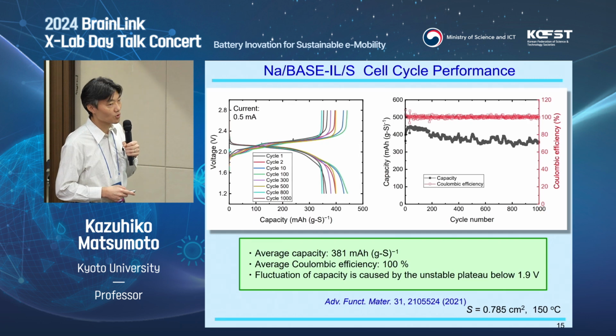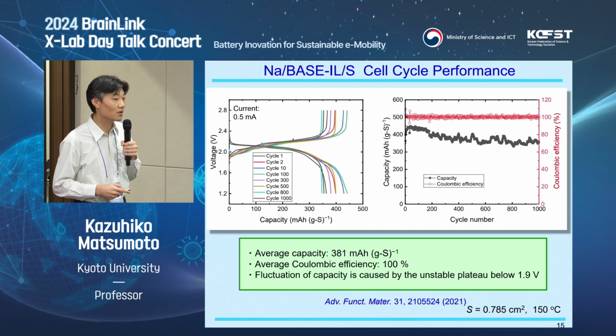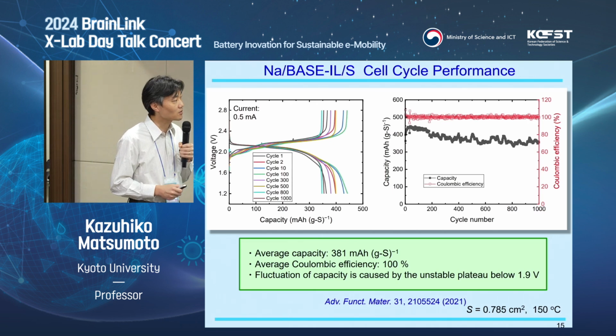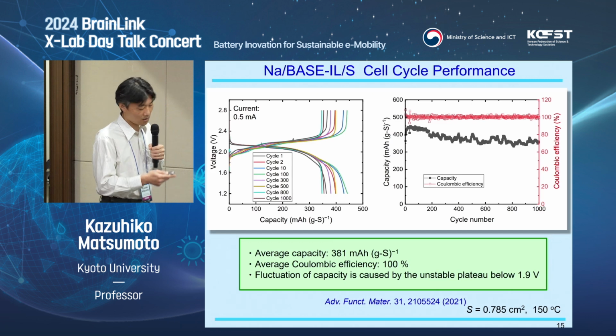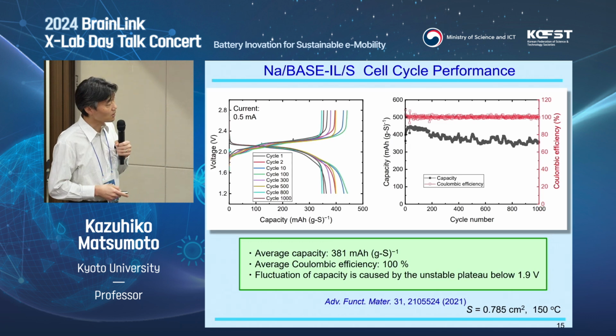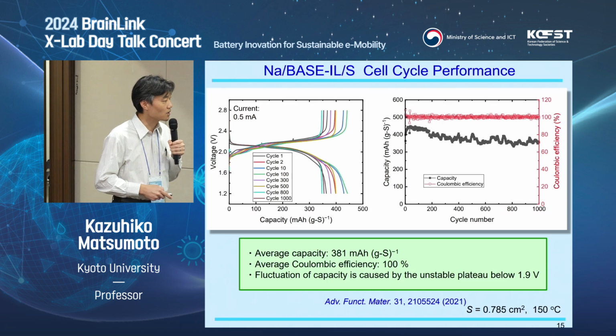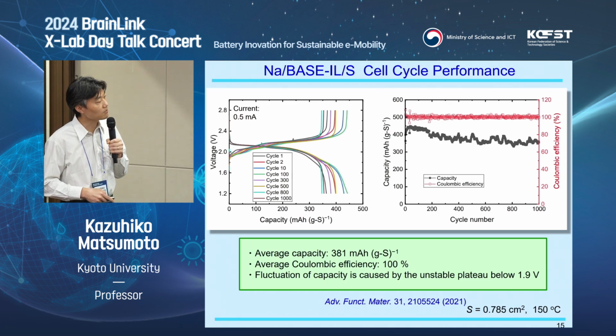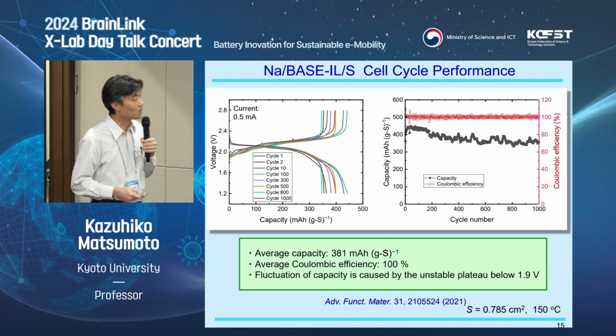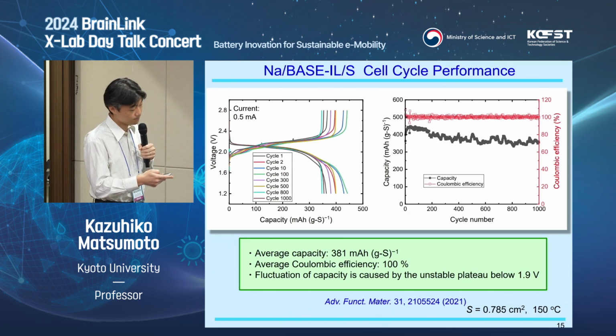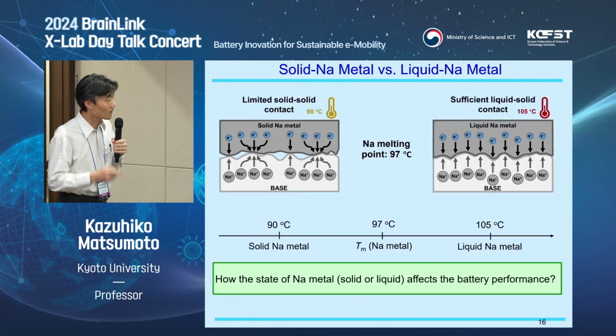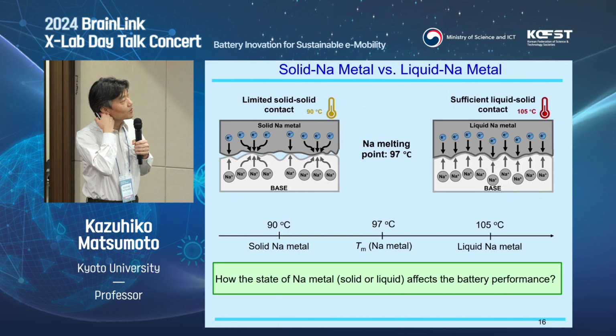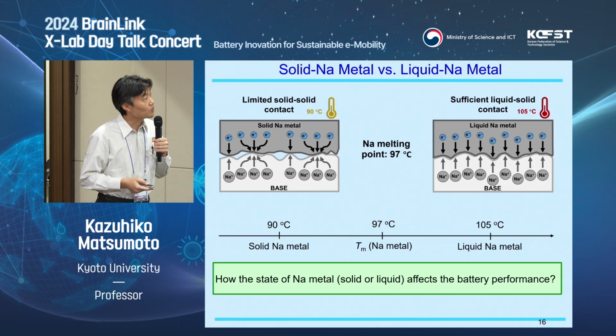We are still not sure why, but in this low voltage region, sometimes we can use that capacity and sometimes we cannot. There seems to be some surface contact that can affect such activity, but still we see the average capacity of 381 milliampere hour per gram, and Coulombic efficiency is nearly 100%. Then we moved to that sodium metal